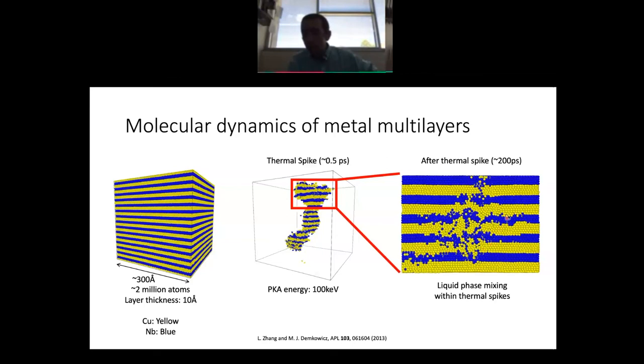So you see that the layers are actually very highly perturbed. The atoms are displaced. The reason why this happens is because copper and niobium, although they phase separate in the solid state, actually mix in the liquid state, right? So if you were to take a high temperature copper niobium liquid, that's miscible, right? So if you have a thermal spike occurring in this material, there's liquid phase mixing occurring inside that thermal spike. And when the thermal spike cools and resolidifies, all of that mixed copper and niobium atoms get frozen in place. Okay? So the question is, do these frozen atoms actually initiate one of these pinch-off events that destabilizes the microstructure of the material?